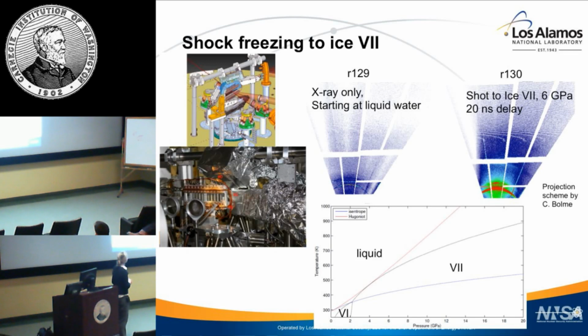So here I show some of the raw data, so it's a little hard to see, but our gold peaks are here, and there's a diffuse signal that develops. This is a shot now up to 6 GPa, 20 nanosecond delay or so, and you can see that there are some changes in the diffraction. It's hard to see in this particular image, but if we now look at integrated traces, it becomes slightly more clear. So here I show our X-ray only. We do have gold, so I do expect crystalline features there. Maybe a little bit of the diffuse signal seen.